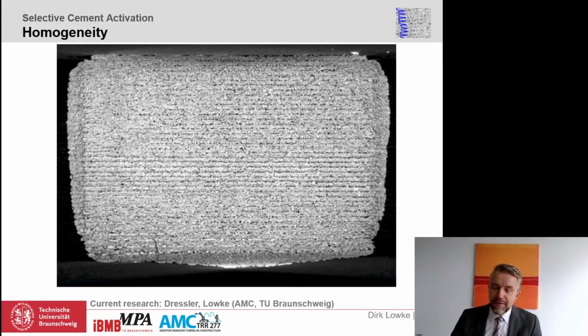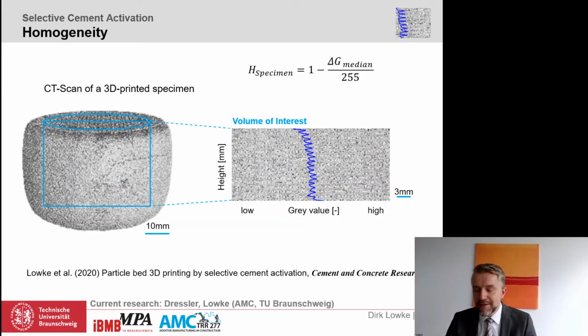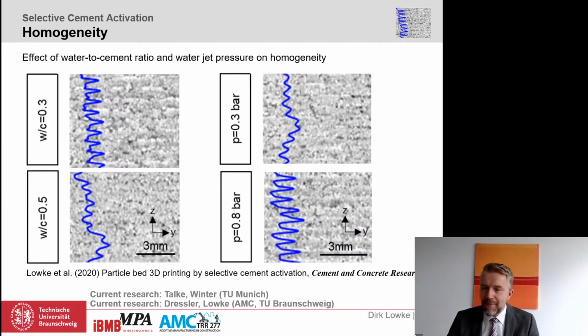To quantify these properties, we used the grayscales of the micro-CT images, as you can see here, to calculate a homogeneity factor. The lower the difference in grayscale between the layers, the higher the homogeneity of the cross-section. And here, exemplarily, you can see some of our results.